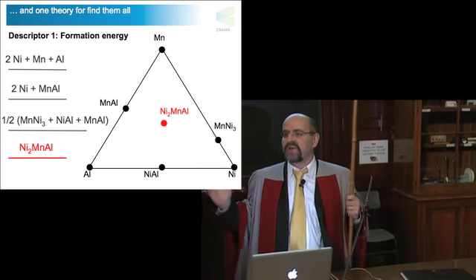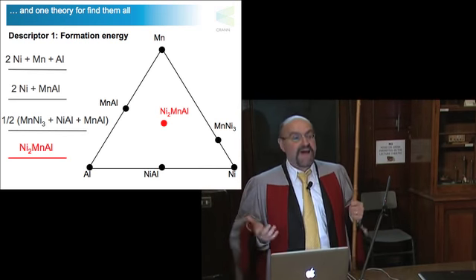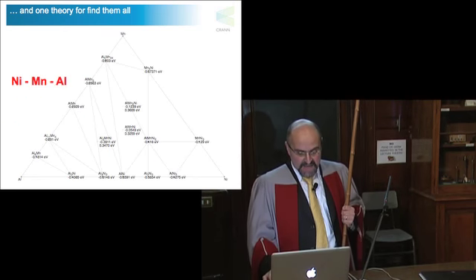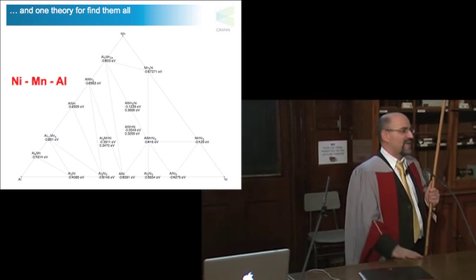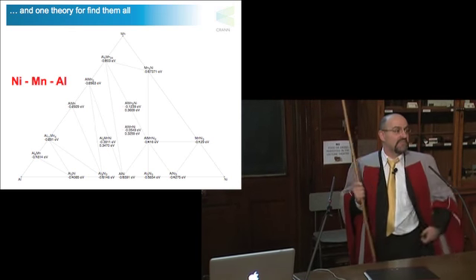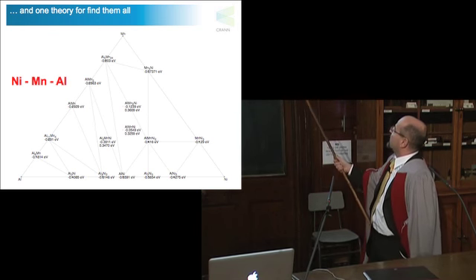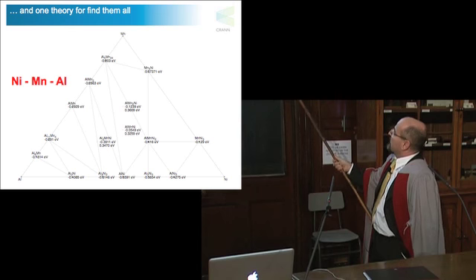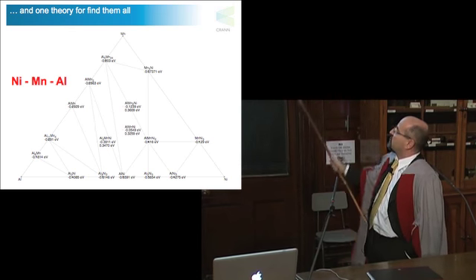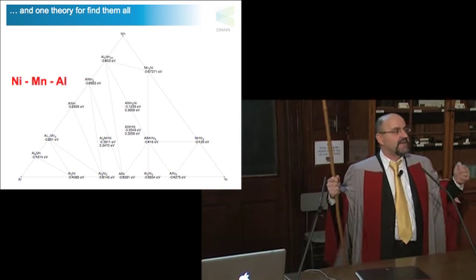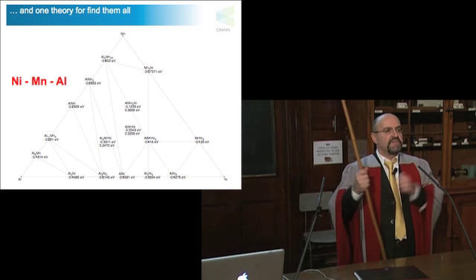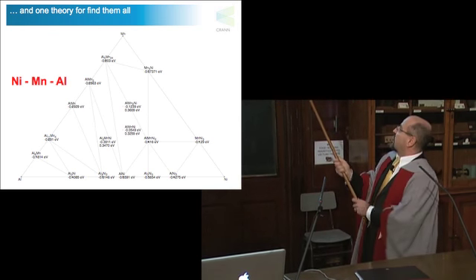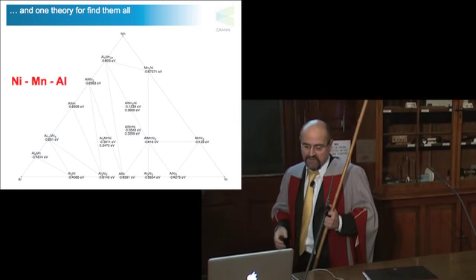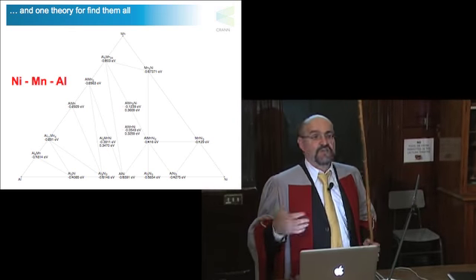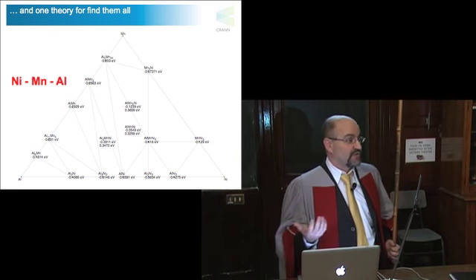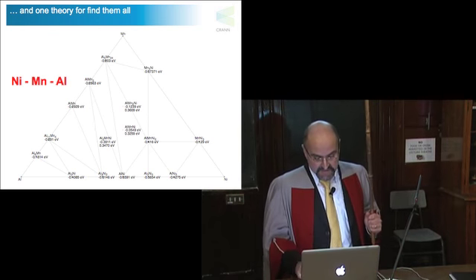And OK, we have a lot of very complicated rules to find out what needs to be calculated and why. And if you do everything, it takes a lot of time, a lot of pain, and a lot of computers. You find out that it's possible to make a prediction. So this nickel, aluminum, manganese alloy is found stable. Three others of the same family are found to be stable against fragmenting into the pieces, but are not stable against fragmenting into different compositions. And we find out that this is also quite an interesting one, because it's potentially a shape memory alloy that preserves the half metallicity. So this is a very interesting one.